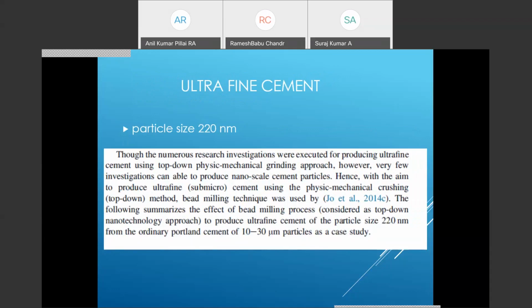Though numerous research investigations have been executed producing ultra-fine cement using top-down physico-mechanical grinding approach, very few have managed to produce nanoscale cement particles. Hence, with the aim to produce ultra-fine cement using physico-mechanical crushing method, bead milling technique was used. The following summarizes the effect of bead milling process to produce ultra-fine cement of particle size 220 nanometer from ordinary Portland cement having size of 10 to 30 micrometer particles, as mentioned in the case study. So you can imagine that the particle size of ultra-fine cement is in the range of 220 nanometer, whereas in ordinary Portland cement, the size of the particles is 10 to 30 micrometer.